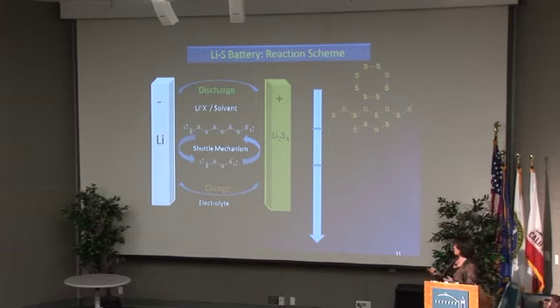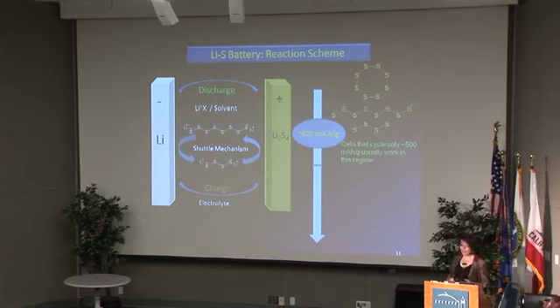So this is to be avoided at all costs. If you can avoid it, that means containing these soluble polysulfides in the positive electrode, and that then allows one to get down to deeper capacities. There are a lot of reports in the literature, should anybody be reviewing lithium-sulfur cells, that present capacities of about 420 or 500, and the fact is that cells that usually cycle about 500 milliamp hours per gram usually just work in this soluble polysulfide regime. So in order to get down to the deeper capacities where lithium sulfide is formed in the positive electrode, one, as I said, has to contain these.